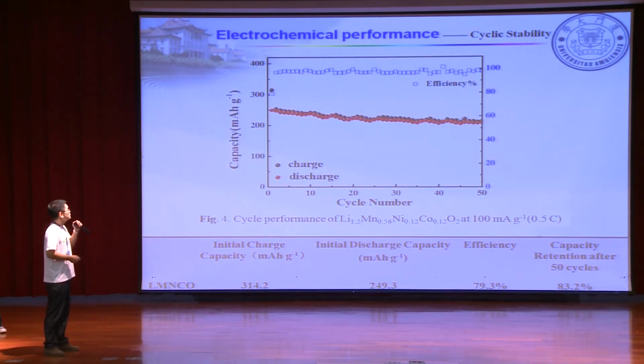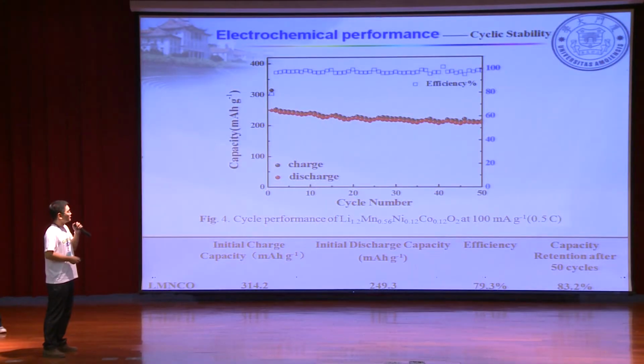And Figure 4 is about the cycle stability of LNCM. After 50 cycles, the LNCM's discharge capacity is also more than 200 milliampere-hour per gram, and the capacity retention after 50 cycles is 83.2%.